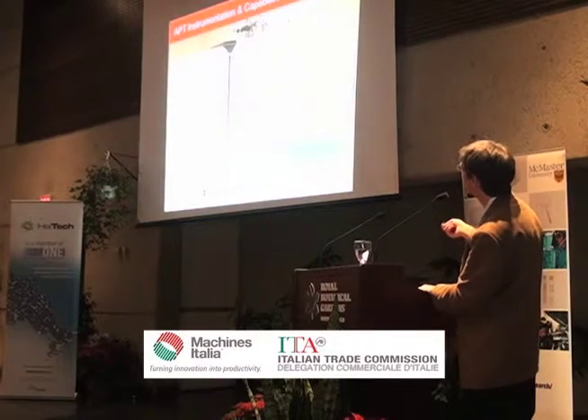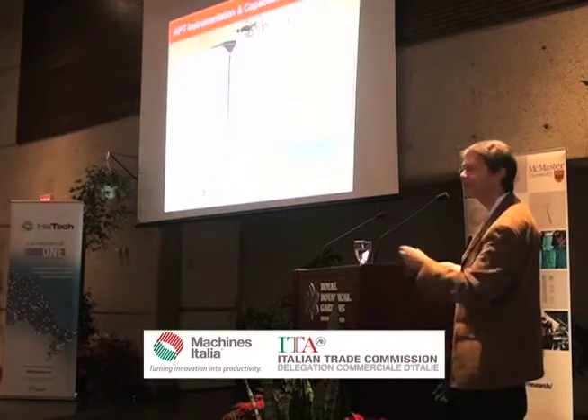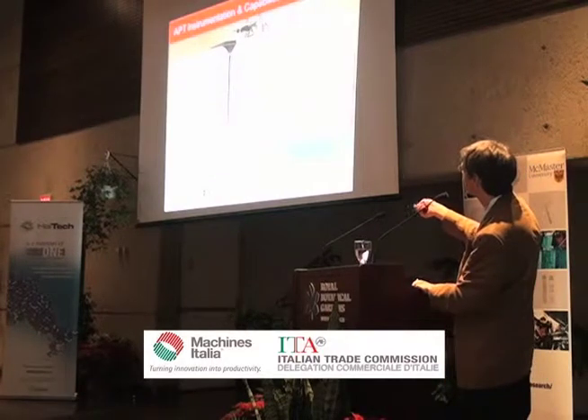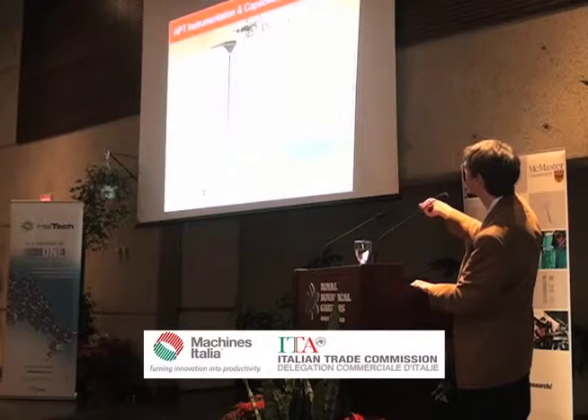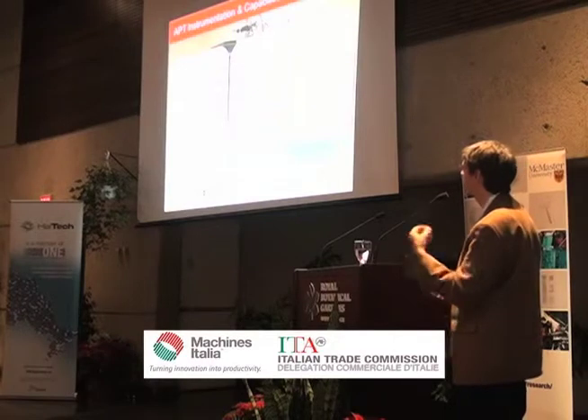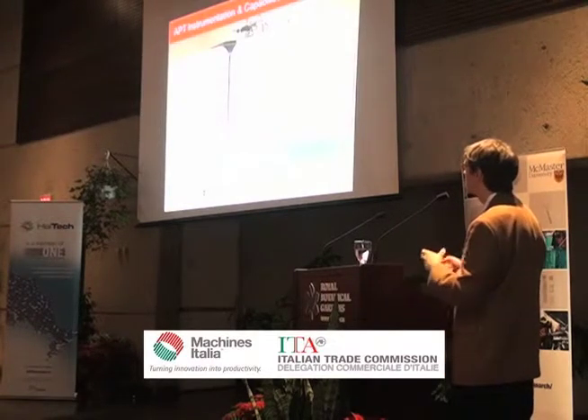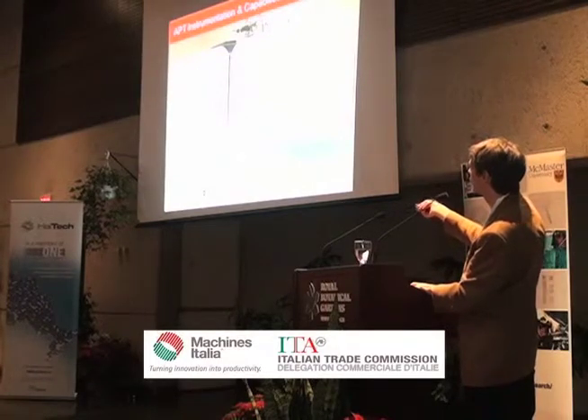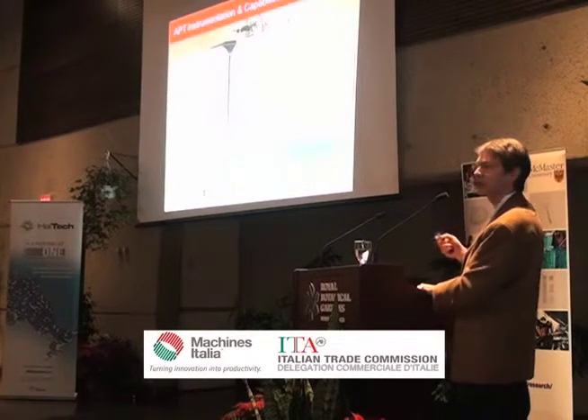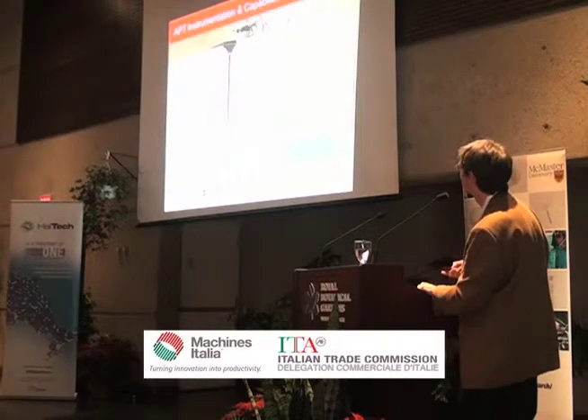And this is the way it works: you have a very thin specimen. You pull atoms with electric field one by one, and these atoms are ejected and they are reflected through this electric field here into a detector. And by measuring how long the atoms take to go to this detector and weighing them in the detector, we can determine which atom we have pulled out of the sample and where they came from. Okay? So we are able to reconstruct, eventually having all the atom positions, what the sample was before we pulled atoms one by one out of the sample.